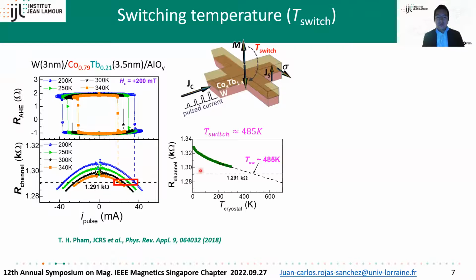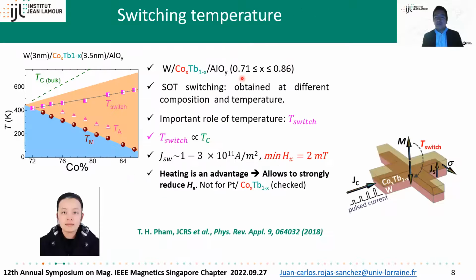We can estimate this temperature using a small current: instead of milliamps, we only use 400 microamps, and we can extrapolate here and estimate the switching temperature for this device at a given composition. And that we can do for the whole series. We change the cobalt concentration, between 72 and 86%, for example. And in all the series, we observe the switching.